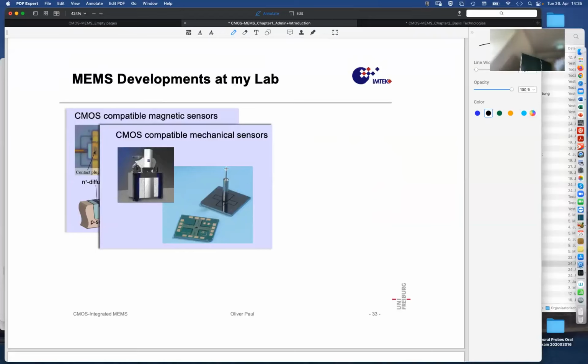And the structure has also been, well, this one has not been fabricated in CMOS technology, but in our clean room, but we have also a CMOS version of this with integrated circuitry on top. So it's an extremely precise instrument with which you can scan the surfaces of micro parts. This little tip is only 100 micrometers around. It's a diamond or a similar ball sphere, and you can then scan over the surface with an accuracy of 10 nanometers. And those 10 nanometers are 3D coordinates. So it's a very, very precise tactile instrument, much more precise than the Dektak or so that you may have seen in the clean room. That can only measure essentially flat profiles, steps.